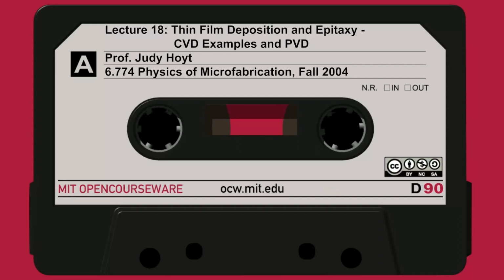Look at the interesting thing about it. Look at the dep rate for oxide. At low temperature, 350, 300, it can put oxide down at a micron per minute. That's an absolutely phenomenal growth rate when you think about it. Yeah, question.